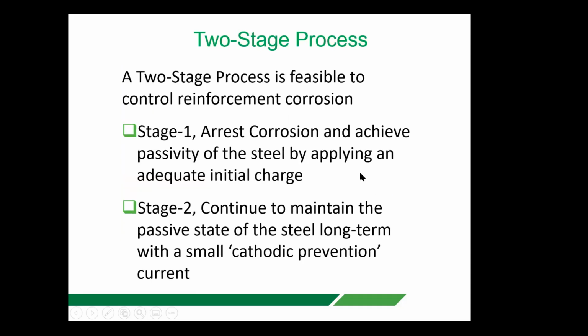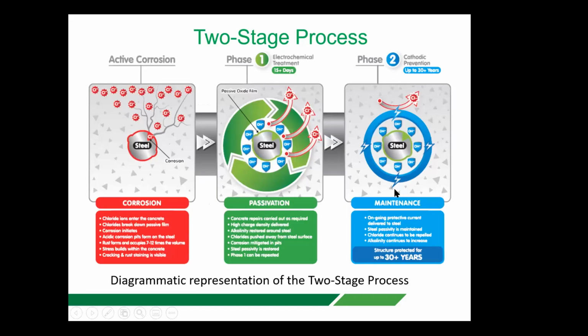Okay, so a two-stage process is feasible to control reinforcement corrosion. Stage one is obviously to arrest corrosion and achieve passivity of the steel by applying an adequate initial charge. And then stage two, where you can continue to maintain the passive state of the steel over the longer term by applying a smaller cathodic prevention type current of between 0.2 and 2 milliamps per meter squared. Okay, so it's basically a diagrammatic representation of the two-stage process.